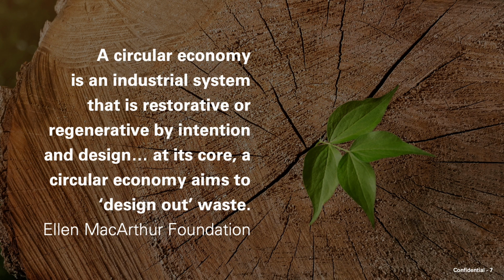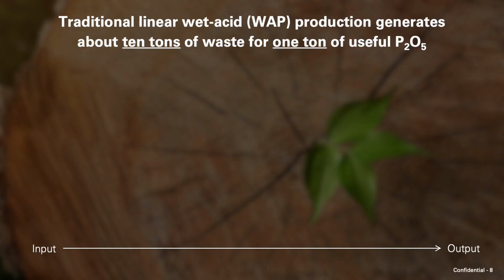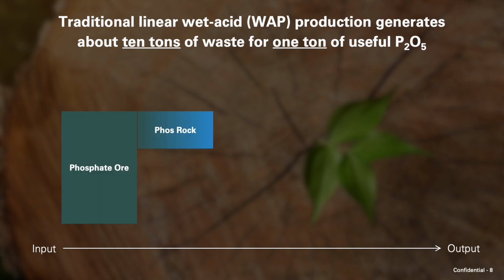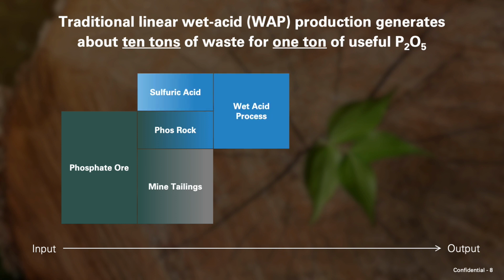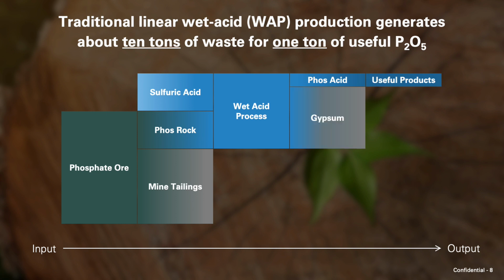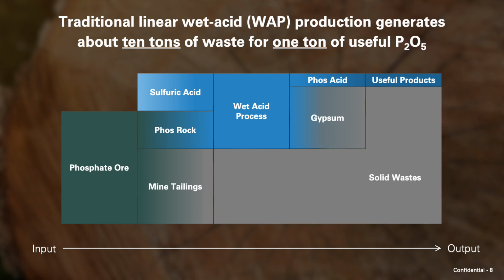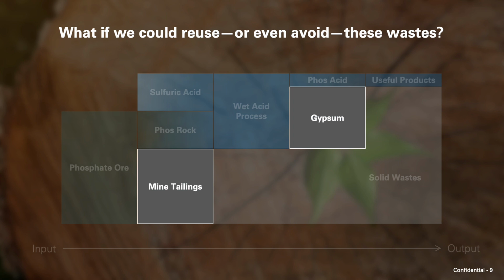Well, there are many definitions of a circular economy. The definition shown here gets at an essential concept. We need to design out waste. So where does waste come from in the phosphate sector? Well, we start with mined phosphate rock, which we then beneficiate to make the useful phosphate rock for the wet acid process. And this generates a lot of mine tailings that contain valuable P2O5. Then we add sulfuric acid, and that feeds the wet acid process, which does indeed make phosphoric acid, but it also makes a lot of phosphogypsum. So, for each ton of useful phosphate products, we get about 10 tons of solid wastes. What if we could reuse or even avoid these wastes?